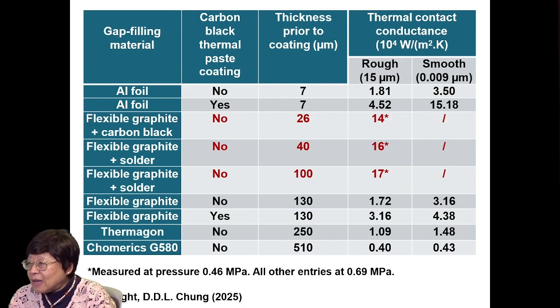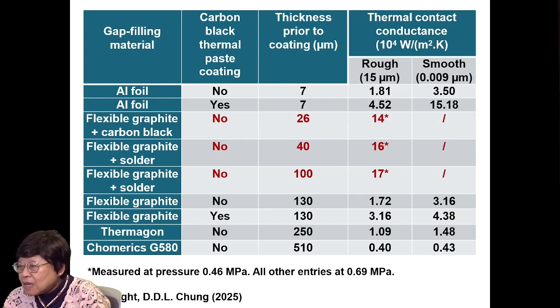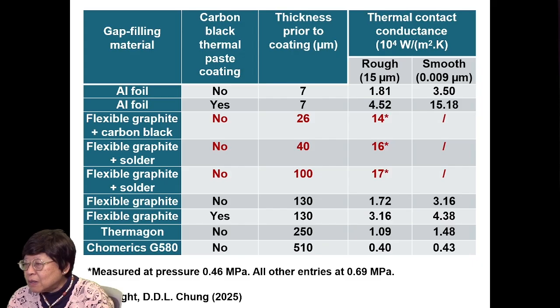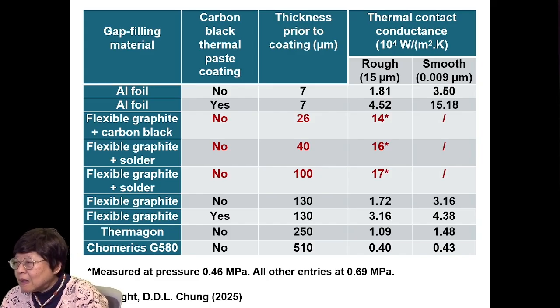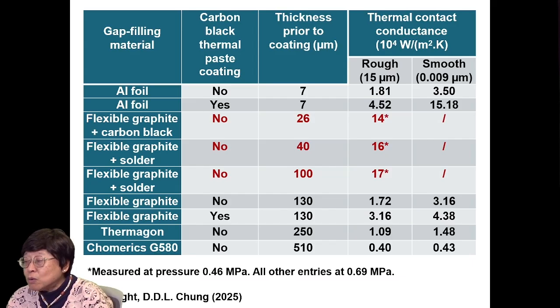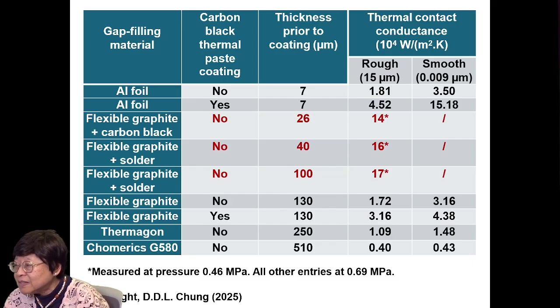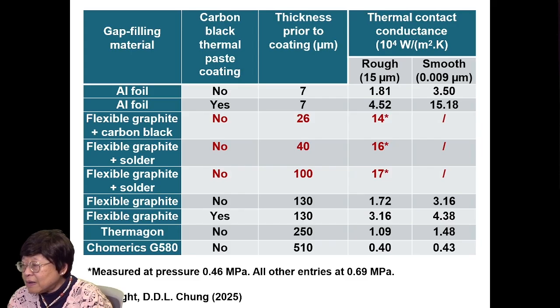Shown here are the flexible graphite with carbon black penetration and flexible graphite with solder. And you can see that the thickness is substantial because it's flexible graphite, and the thermal contact conductance from 14 to 17, note that there's no coating, right? This is all inside, carbon black inside, the solder inside, and the thermal contact conductance for the rough case is shown here. 14 to 17 is the best. It's the best in this list.